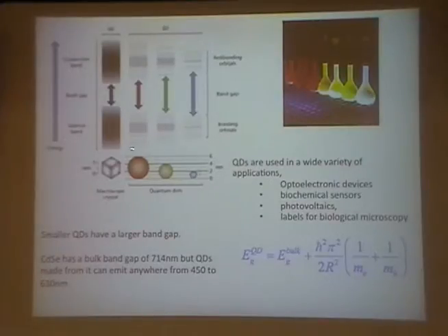So the one other point here is that by changing the size, we're changing the energy structure. So even though the bulk semiconductor will have a certain gap, give a certain emission, like maybe silicon's giving 1.1 eV, if you take that material and just make it smaller and smaller, you can have different emissions. So cadmium selenide has a bulk gap of 714, but if we make quantum dots from it, they can emit anywhere between 450, which will be really blue, up to 630 or even more, just by changing the size. So it's a really tunable material.